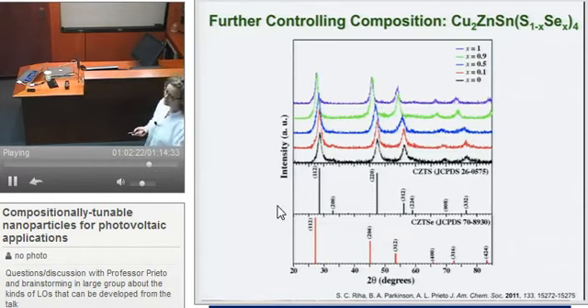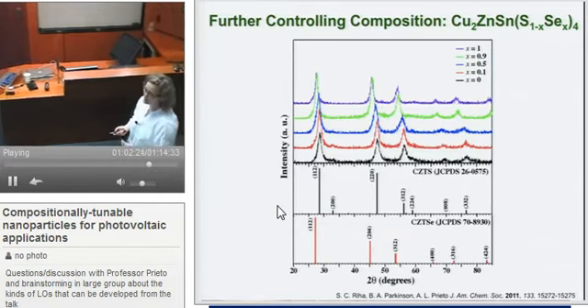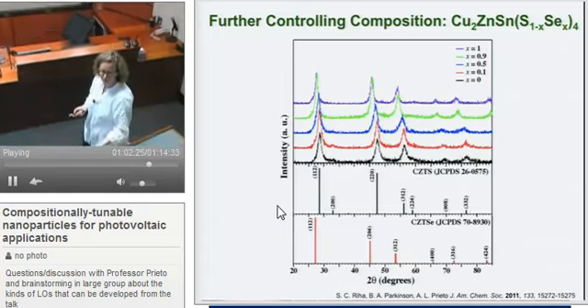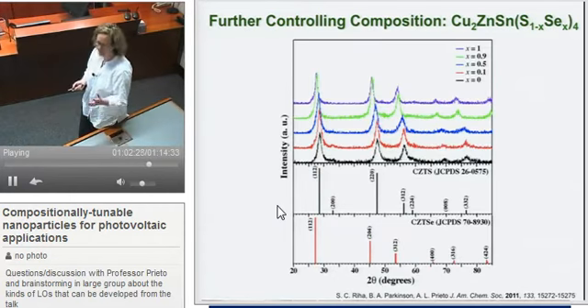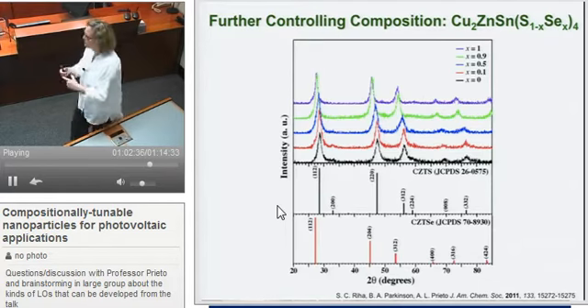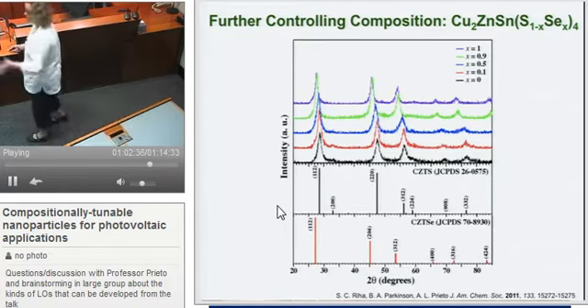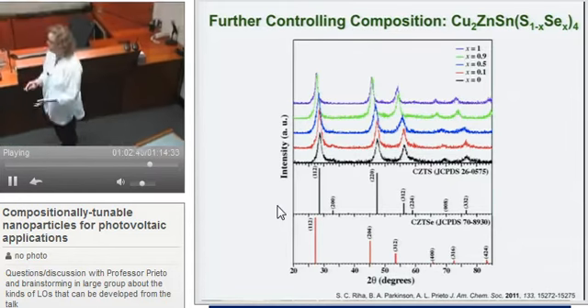Now, I told you we used allylamine as a reducing agent. It does not reduce selenium, so you can't dissolve it. So she had to use allylamine for the sulfur and sodium borohydride for the selenium. So now she had 3 syringes she was injecting at the same time. And she did a lot of controls to try to make sure this was actually real.